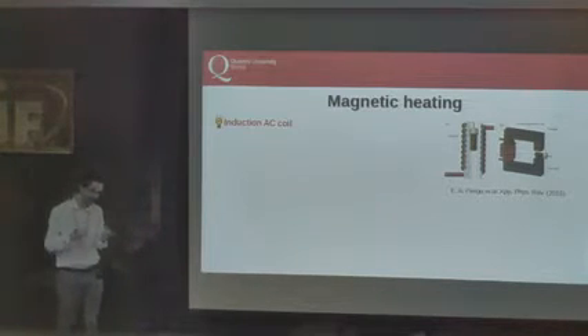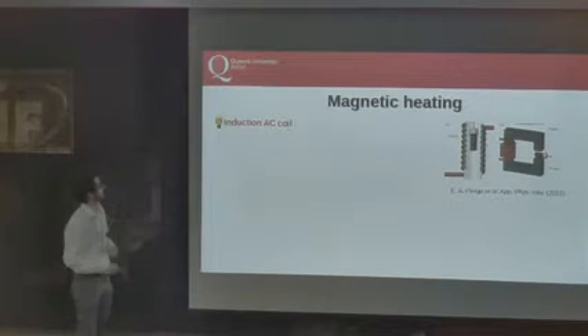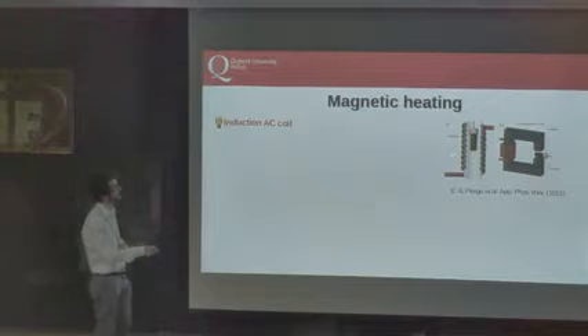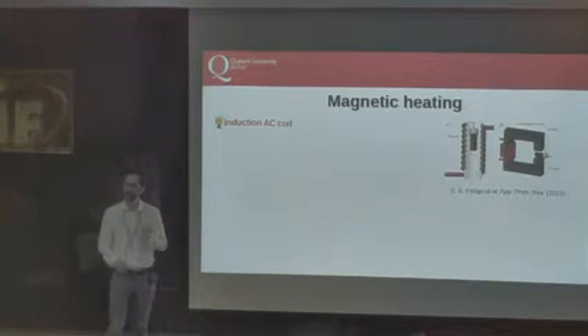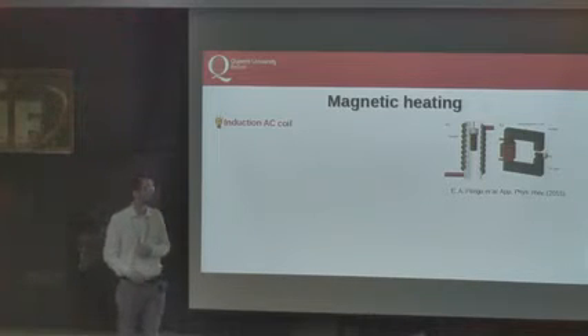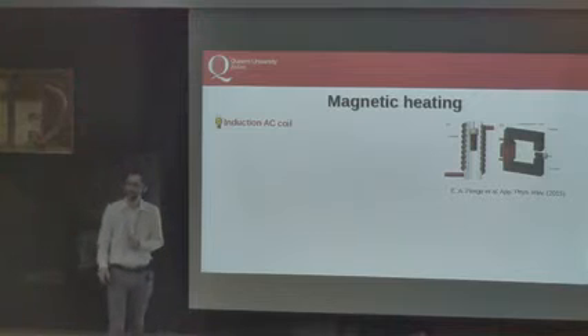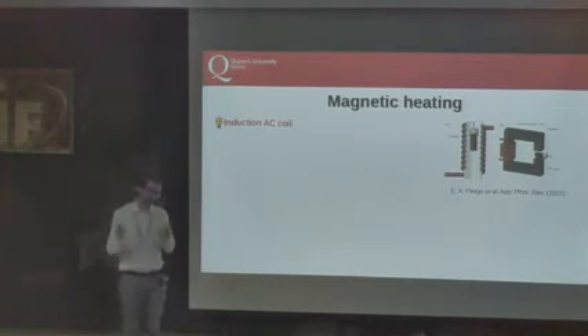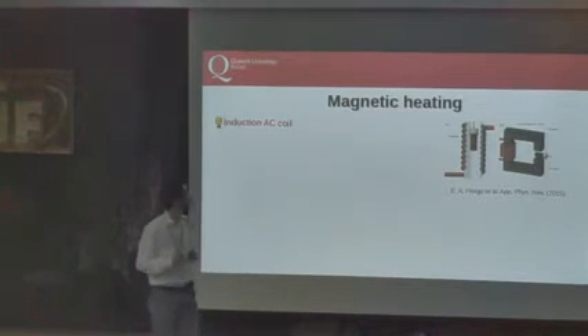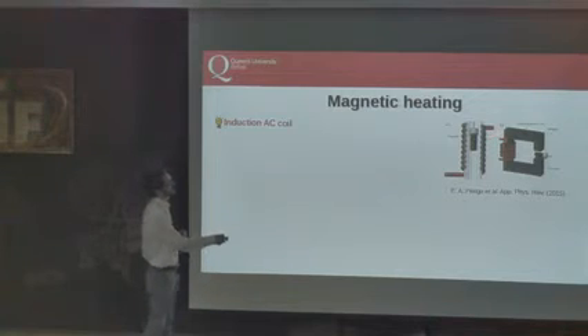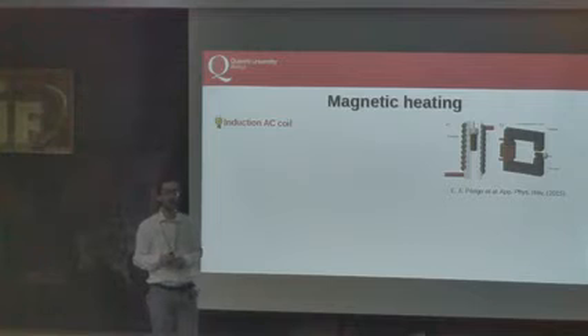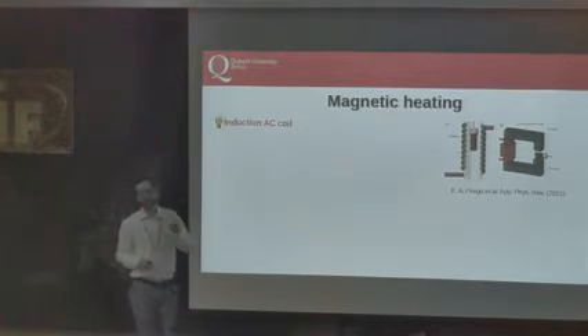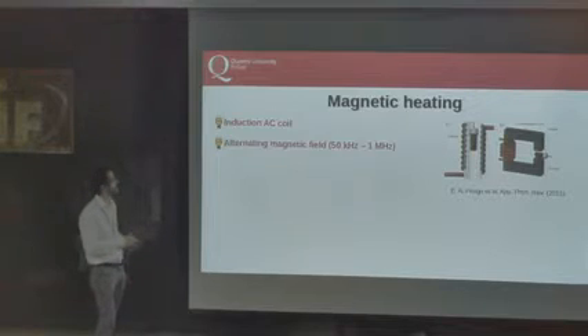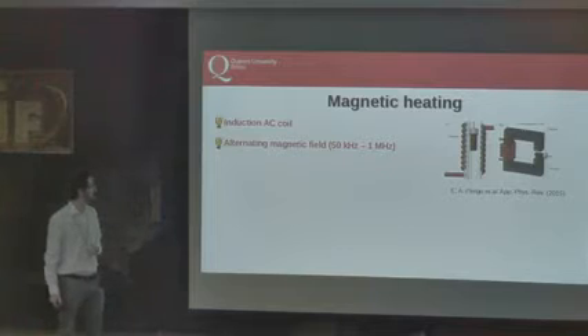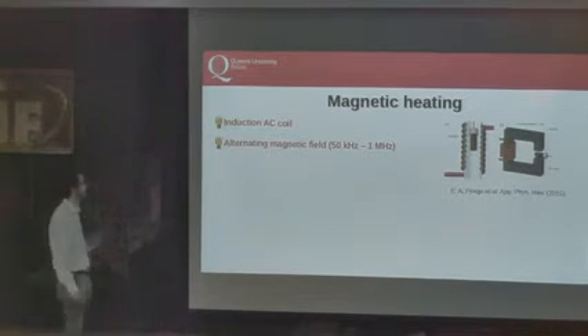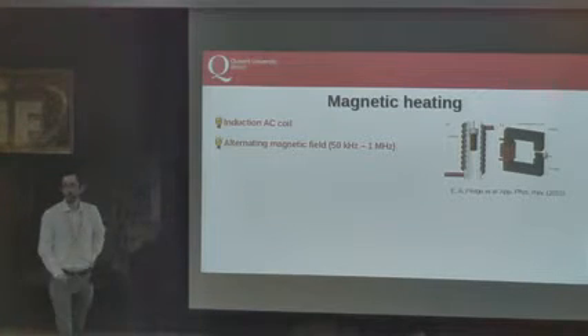The external source of energy that we commonly use is an alternating external magnetic field, which is usually produced either with a coil. We usually have a coil in the laboratory at Queen's University. Other laboratories have a ferromagnetic core. So we have our nanoparticles that have been synthesized in a way that I'm going to tell you in a second. They are put in a little vial. The vial is placed here in the coil, and an alternating AC current is passing in the coil, and then as a response there is an alternating magnetic field. The frequency of this alternating magnetic field is in the radio frequency range, so RF, roughly 50 kilohertz to 1 megahertz.